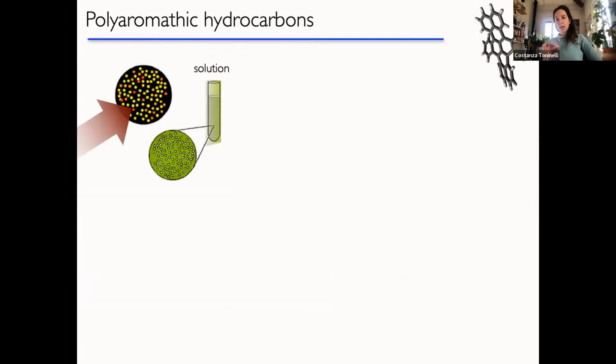In particular, which type of molecules am I talking about? For these applications, we are considering polyaromatic hydrocarbons. These are very small molecules that are planar and rigid. And this is very important to decouple from the phonon bath, in a sense.